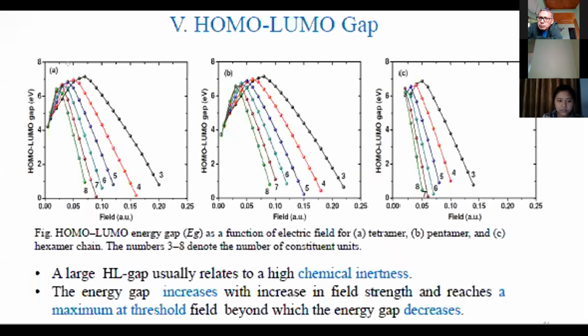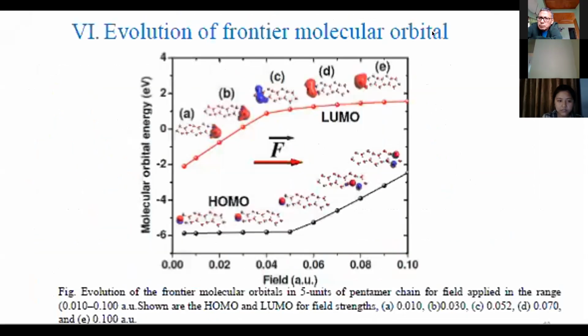So this peculiar behavior of the opening, then the closing of the HOMO-LUMO gap, and then again increasing and, after some point, decreasing is seen in this system. And this we have tried to understand in terms of redistribution of molecular orbitals. Here we have plotted molecular orbital energy versus field. For the LUMO, up to a certain field, the LUMO energy increases, and after one point, with the increase in the field, the LUMO energy almost saturates.